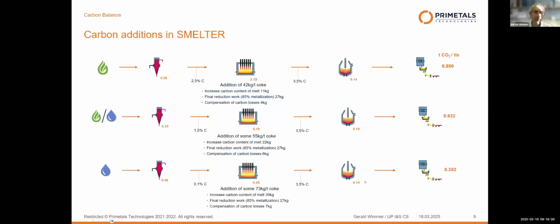Let's start with the first one, with the carbon. Here, a quick overview of our different carbon levels of DRI. So today's direct reduction plants all are running with natural gas, having typically a carbon level of 2.5% of carbon in the DRI. And as we have a two-step process, we need a metal from our smelter that has sufficient carbon for smooth BOF operation. And this depends, of course, on the plant. What is the hot metal logistic? What is the hot metal temperature I can still achieve to get charged to the converter? What is the final tapping target from the converter? What's the size of the converter and the specific heat losses?